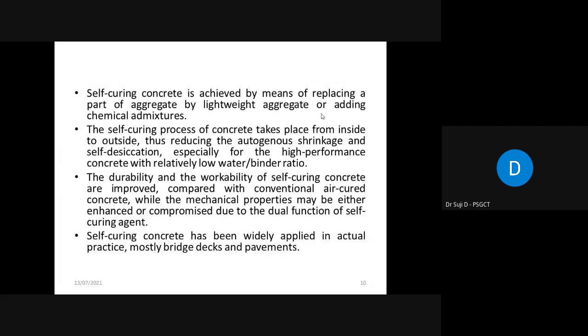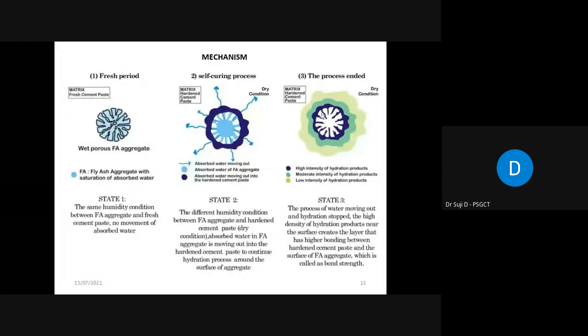Then self-curing concrete has been widely applied in actual practice, mostly bridge decks and pavements. And this is the mechanism. This is similar to what I have explained. Here they have attempted fly ash aggregates. So wet porous fly ash aggregates are used, under the same humidity condition, under hygral equilibrium. If relative humidity difference is 0, then the same humidity conditions exist between the fly ash aggregates and fresh cement paste. There will not be any movement of absorbed water, right? Once the humidity difference arises, the mechanism starts.